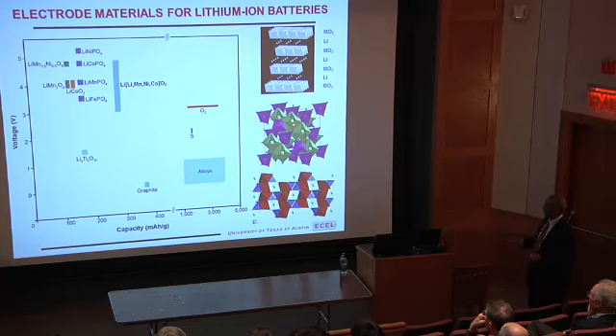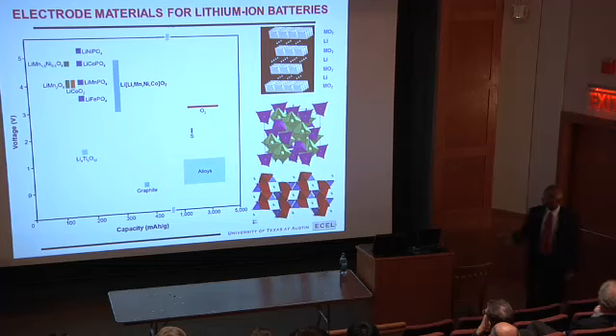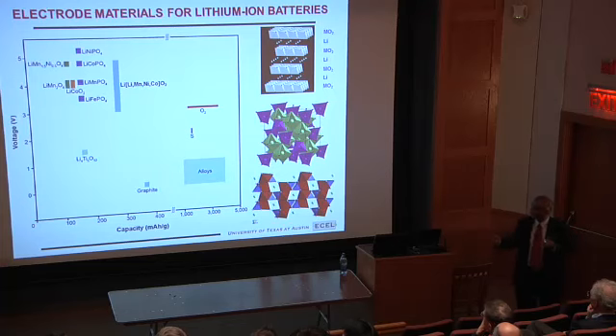Spinel, LiMn2O4, has a three-dimensional structure. So it has three-dimensional lithium-ion diffusion. Both of them have edge-shared octahedra, so the metal ions can directly see each other. Therefore, there is a good hopping conduction. In the case of lithium cobalt oxide, actually it is metallic, so electronic conductivity is not a problem. In the case of spinel, good hopping conduction because of edge-shared octahedra, the metal can transfer electrons. So that's a fairly good hopping semiconductor. So conductivity is not an issue.